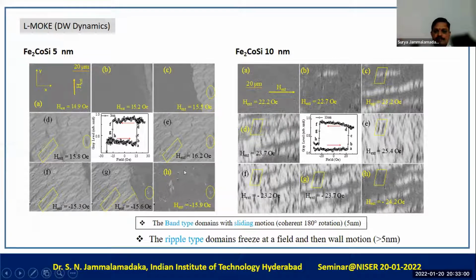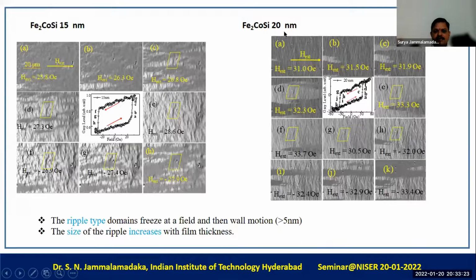So as you could see here in the domain images, for the film with thickness 5 nanometers, we do see band type domains with sliding motion. However, when the thickness of the film is more than 5 nanometers, we do see ripple kind of domains. For 15 nanometers and 20 nanometers, the ripple size increased. And again, the ripple kind of domains persist for all the thin films except for 5 nanometers. On top of that, we do see higher anisotropy regions at some places in the films.